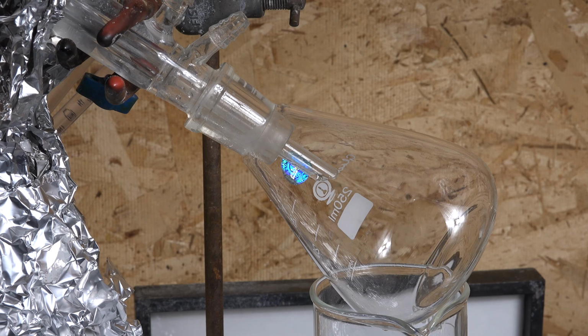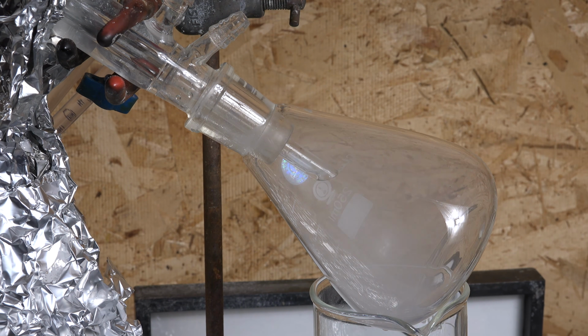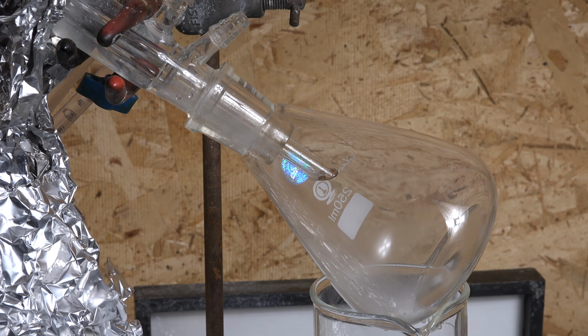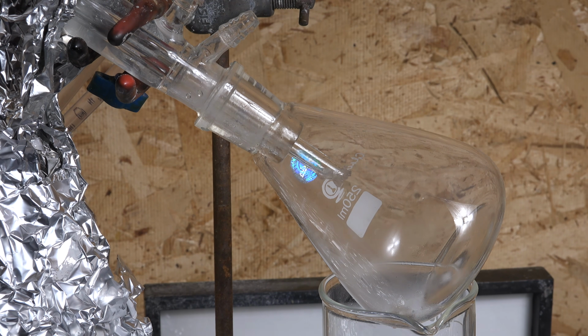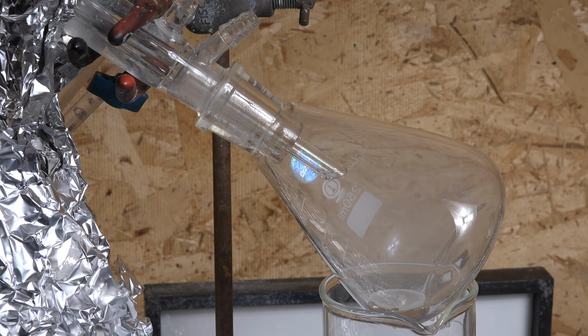And there we go. I started at 200 Celsius at first, and then raised it to 300 Celsius after half an hour, and held it for another half an hour. Then I raised the temperature 10 degrees every 10 minutes until I noticed it was fuming at about 360 Celsius. The better insulation meant the reaction started at a much lower hot plate temperature. Previously, I needed 490 degrees Celsius. Since it's a lot cleaner this time, I didn't have to discard the first few drops of sulfur trioxide.